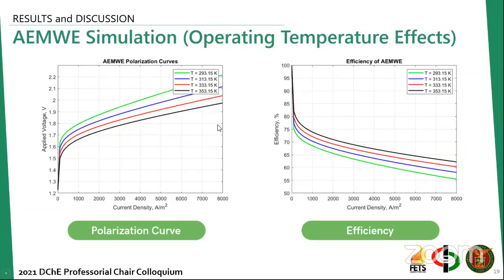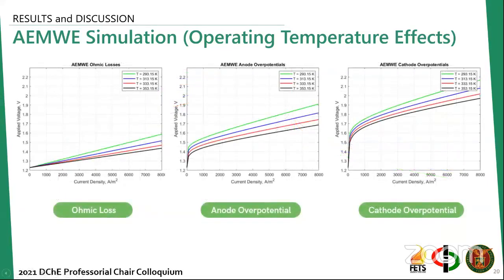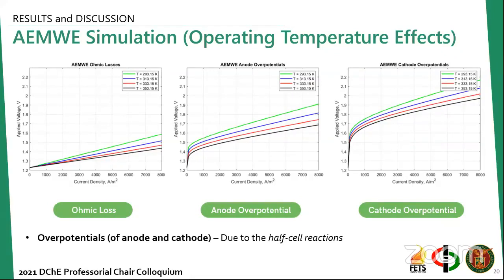Then this is further exhibited in the next set of plots, which show the losses such as the ohmic loss and the overpotentials of anode and cathode. The overpotentials are due to the half cell reactions, and they contribute more voltage loss compared to the ohmic loss. Normally, the ohmic loss is mostly caused by the ion transport in the membrane, thus increasing the ionic conductivity of the membrane may lower the ohmic loss in the system.